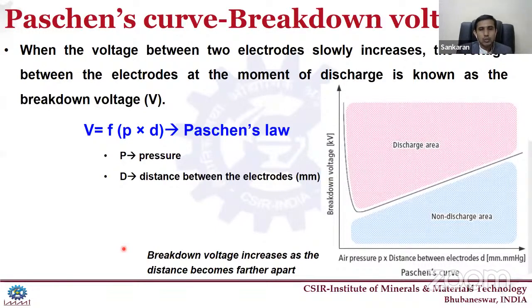From this Paschen curve, you can see this is the breakdown voltage, and this is the pressure and the distance between the electrodes. Once the plasma starts from here, this is the discharge of the plasma. Then, as the pressure and the distance continue to increase, we can see the breakdown voltage also increases. So this point we call the breakdown voltage. The breakdown voltage is a function of the pressure and the distance. The distance is the distance between the 2 electrodes, on a millimeter scale. So the breakdown voltage increases as the distance between the anode and the cathode increases. The breakdown voltage is a very key parameter to be analyzed when we are talking about microplasma.